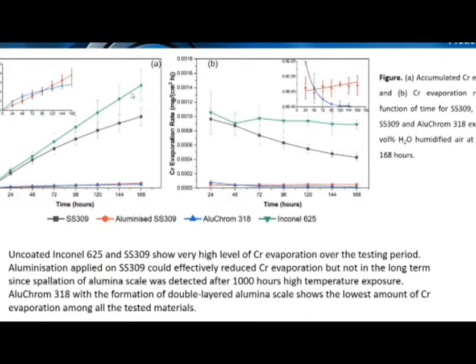So yeah, in figure A, we can see accumulated chromium evaporation of the 4 different alloys tested for 168 hours. Figure B is the chromium evaporation rate of the 4 different alloys. So as we can see, Inconel 625 has the highest amount of chromium evaporation because Inconel 625 produces pure chromium oxide as a protective layer during high temperature exposure. For 309, when stainless steel 309 is exposed to a high temperature environment, it produces a chromium manganese spinel layer on the surface, which has a lower chromium evaporation compared to Inconel 625.